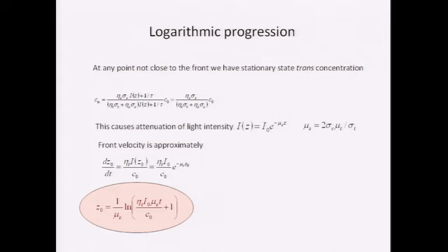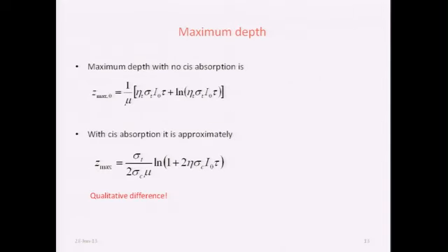So then we can use this simple rate calculation for how the front progresses, and we get a differential equation which one can solve. We see that the maximum depth we reach at a given time increases logarithmically with time and with the input intensity. Not linearly, but logarithmically. Of course, for short times this is linear. For long times it becomes logarithmic, and then at the end it saturates. But we can also get the maximum depth we can reach at infinite time.